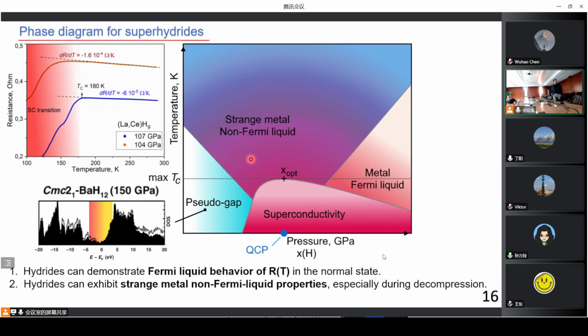I see. So why do you say on the left of the phase diagram there is a pseudogap-like state? Yeah, it's exactly the case we discussed, when the superhydride or lanthanum hydride has a negative temperature coefficient of resistance. It's a semiconducting-like behavior, and ab initio calculations also show us that in some of the superconductors, such as BaH12, this pseudogap should be observed. It can be calculated, and the calculations correspond very well to the experimental observations. So it should exist according to the calculations, and we found the first signs of a pseudogap phase in H3S and the lanthanum polyhydride as well. I see. Okay, thank you very much.